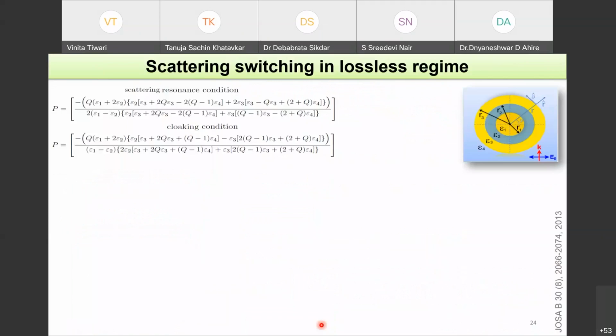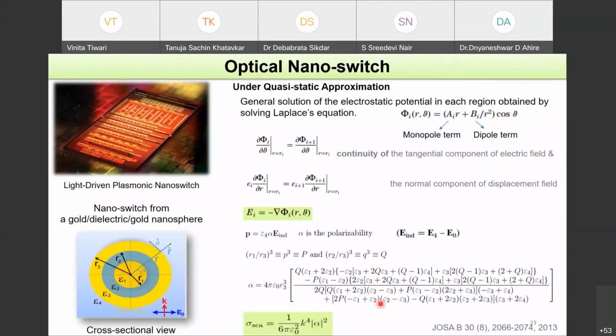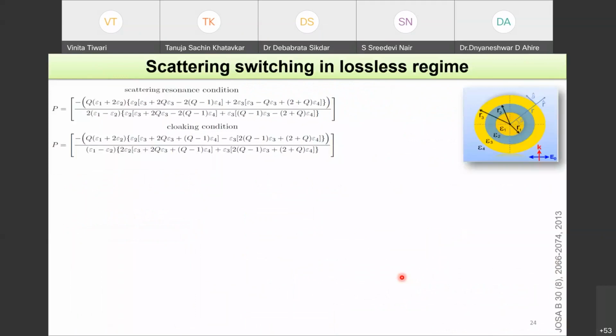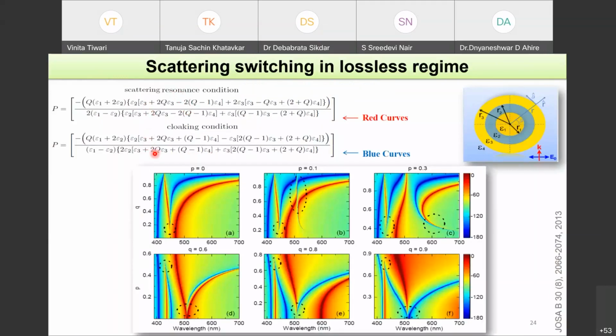So if you look into the alpha expression, alpha has got a numerator and denominator. So when the denominator goes to 0, you get a scattering resonance. So it's a high scattering state. But when the numerator goes to 0, you get a low scattering state or a cloak state. So if we obtain those expressions explicitly, that where scattering resonance is taking place and where cloaking resonance is taking place, you obtain these two conditions. And then you can plot them as a function of physical parameters.